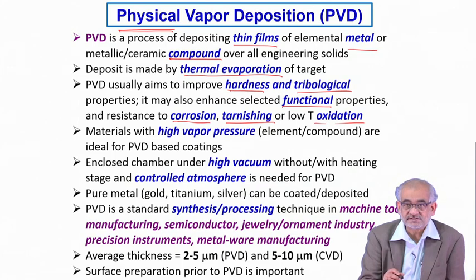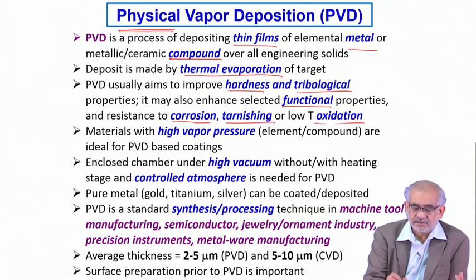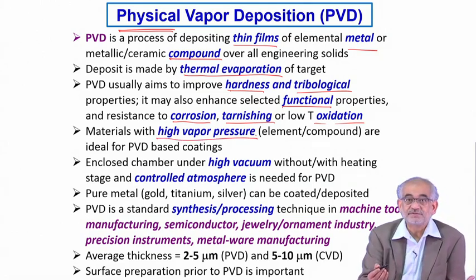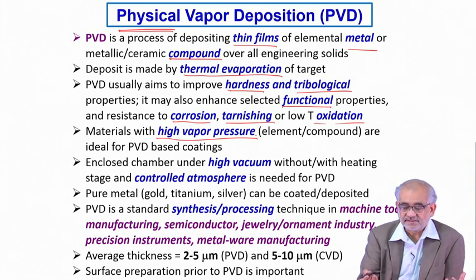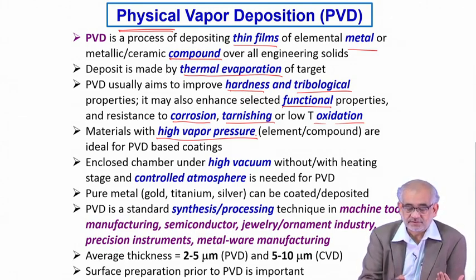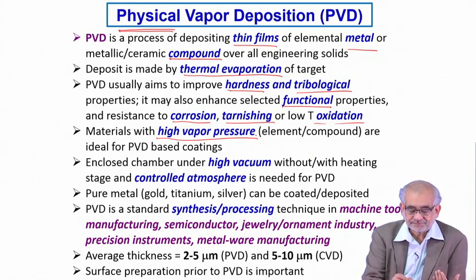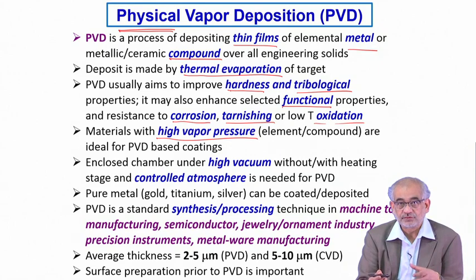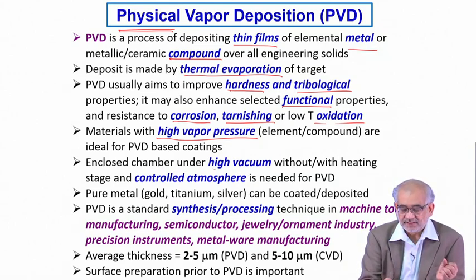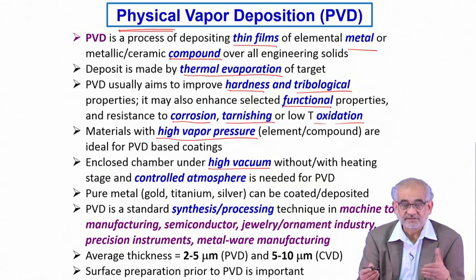The difference, as already mentioned, is that we are dealing with fairly thin films. We need materials with very high vapour pressure so that by heating we can easily take them into the vapour state and they can create a saturated vapour pressure around the component to be coated. We take the material and component both inside an enclosed chamber, then evacuate and create fairly high vacuum — over 10 to the minus 5 millibar or even higher vacuum.